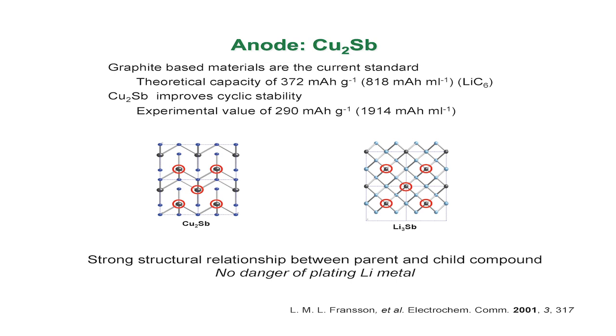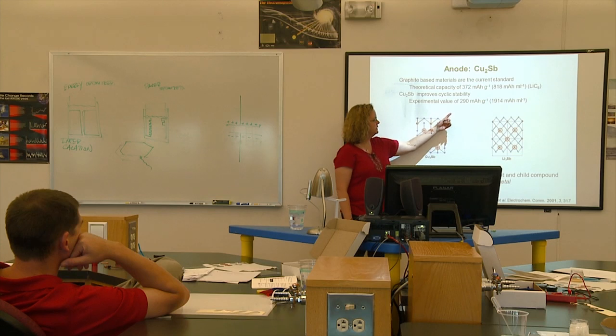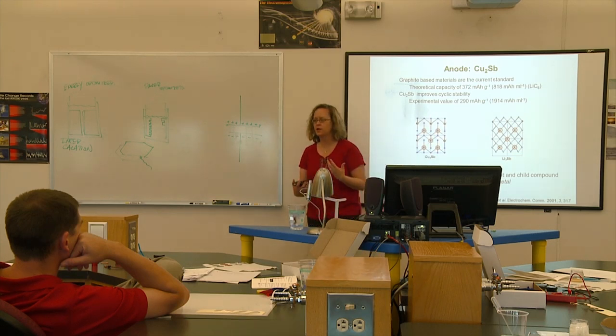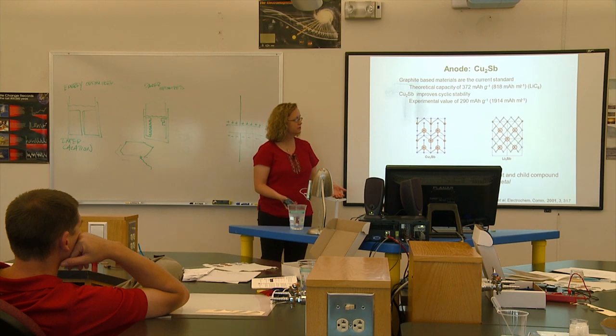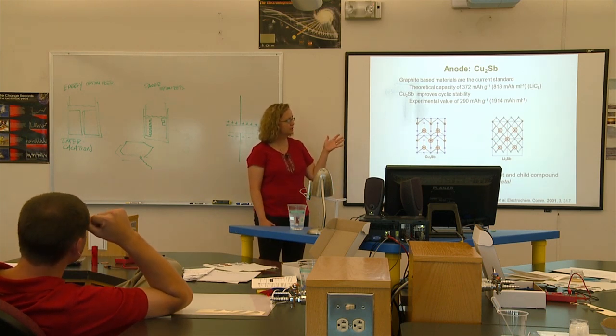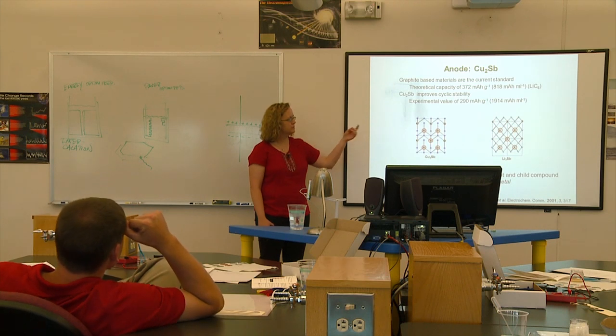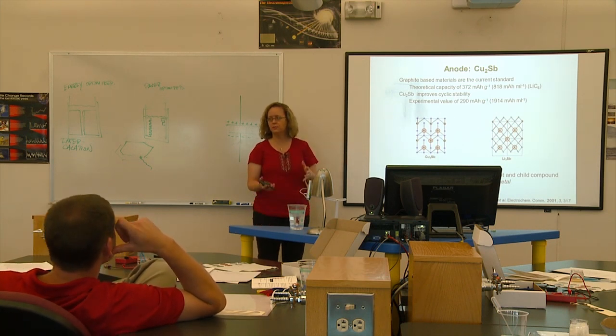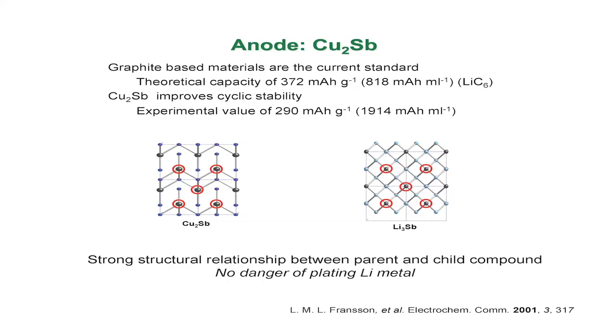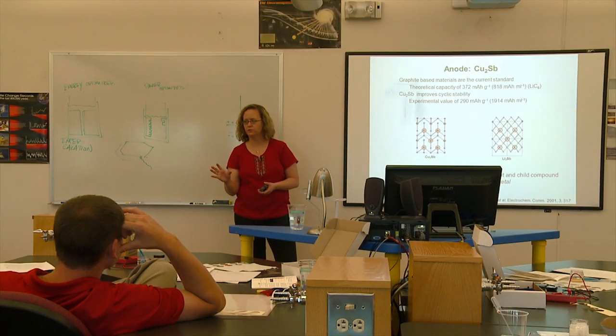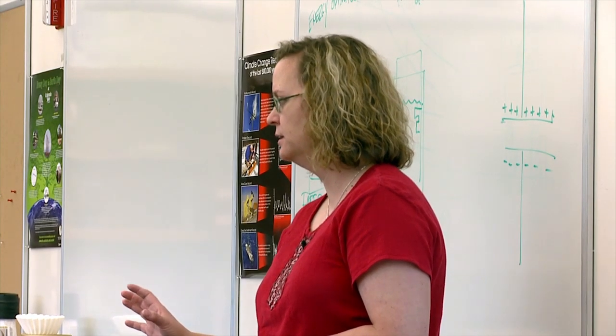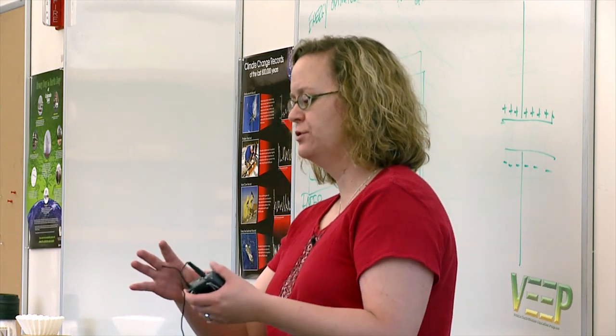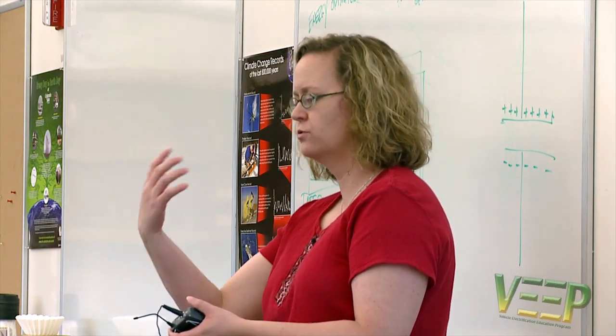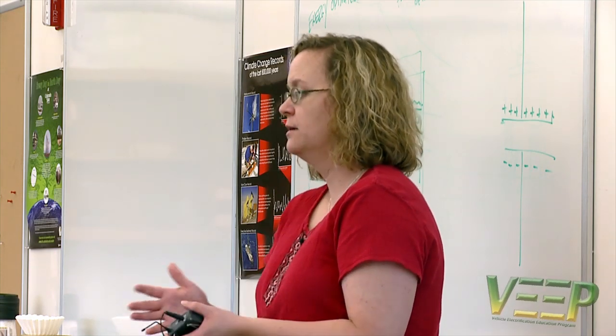Now, graphite, if you think about mass, has a capacity of 372 milliamp hours per gram. Copper antimonide is lower than that, it's 290, and that's because antimony is such a heavy element. But if you look at it volumetrically, graphite's at about 800 milliamp hours per milliliter, and copper antimonide's at about 1900. So it stores a lot more per unit volume, and we chose that intentionally because right now, all lithium-ion batteries are limited by their cathode material. There are no cathode materials that have really good capacity. So we wanted to have a structure where a lot more of the volume could be used to store cathode material, so we wanted an anode that would take up less space.